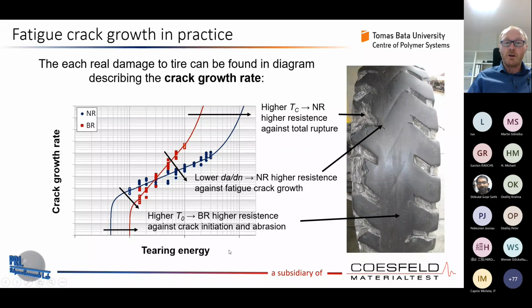And if we follow some really basic polymers and focus only on polymers like natural rubber and butadiene rubber, then we can very clearly see, for example, that with increasing natural rubber, in this low tearing energy region, a higher resistance against crack initiation and abrasion or wear will be achieved. In the middle part, for stable crack growth, that means for a lower fatigue crack growth rate, NR delivers a higher resistance against fatigue crack growth.